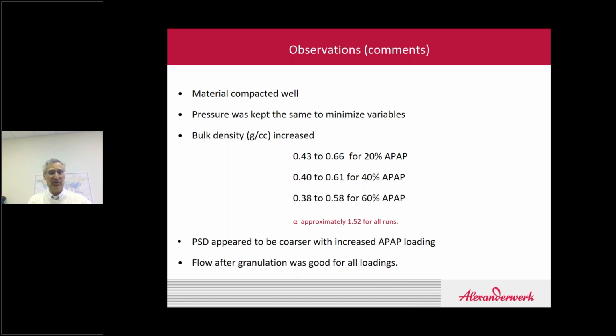And interesting, if you look at all of these bulk density analyses, it gives you an alpha, as we talked about, of approximately 1.5, 1.52 for all the runs. Also interesting to note, the PSD appeared to get a little coarser as we had an increased drug loading. Not uncommon. But the bottom line is the flow after granulation was good for all the loadings.